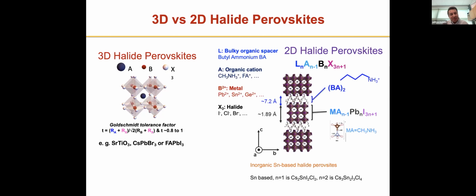Now, in addition to this, if I add one more bulkier organic cation, for example, if I take something like a butyl ammonium cation, which has 4 carbon atoms, and if I put this into this mix, then what happens is that I do get my perovskite structure, but because this butyl ammonium is pretty large, it can't quite fit into the cage. And so what you end up getting is a layered structure. It organizes like layers as it's shown in the picture here.